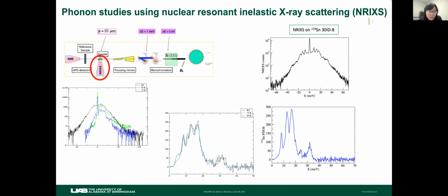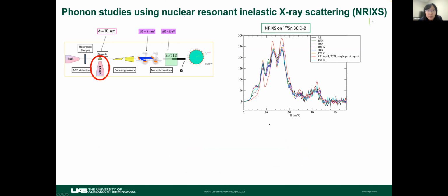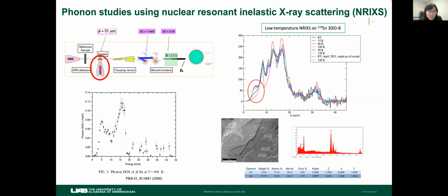Okay, and then so we collected data at several temperatures, and the inconsistency is there. And in a separate run, we used a large single piece of crystal, and we didn't see an obvious phonon mode around the 5 milli-electron volt. So to look into that inconsistency, we took the same piece of crystal we had studied earlier that shows this pronounced phonon mode around 5 meV.